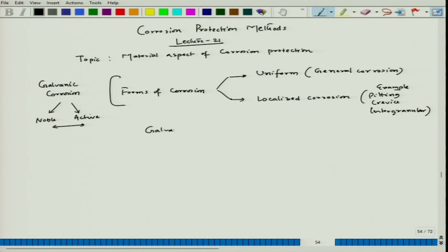Typically even if we consider pitting or crevice, during the formation stage of pitting as well as crevice, a differential aeration cell happens in the pit or in the crevice part. So, the crevice or pit part becomes anodic and the rest of the surrounding metal surface would become cathodic. So, again that galvanic effect, a localized galvanic effect, comes into picture. So, whenever we talk about the initial formation part, let us understand galvanic corrosion, I mean to say two metal corrosion. Sometimes it is also called two metal corrosion. Now, in a component, we can have one part as anode and one part as cathode. Okay. So, they can be joined by welding.